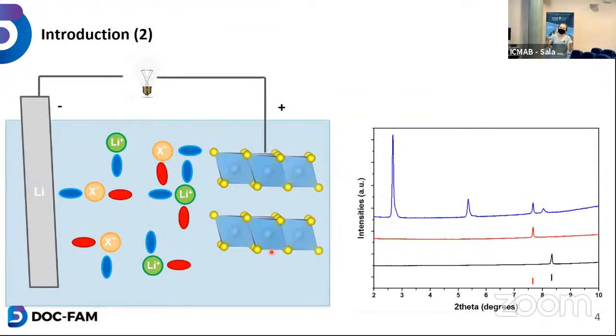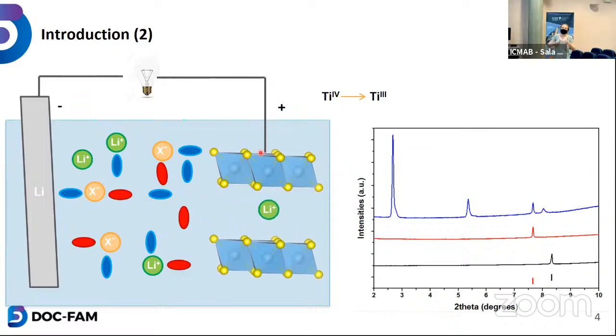This is a schematic representation of a lithium versus titanium disulfide battery. You have your electrolyte that is composed of lithium, an ion depending on the salt, and solvent molecules. When you are discharging your battery, you will release one lithium ion as well as one electron. The electron will go through the electrical circuit, and the titanium disulfide will get reduced. To compensate this charge, one lithium ion will enter in the layers of the titanium disulfide, and you can actually see the change in the structure of the material with X-ray diffraction. Here I presented one pattern of the starting material, titanium disulfide, and one pattern at the end of the reduction, so with lithium intercalated.